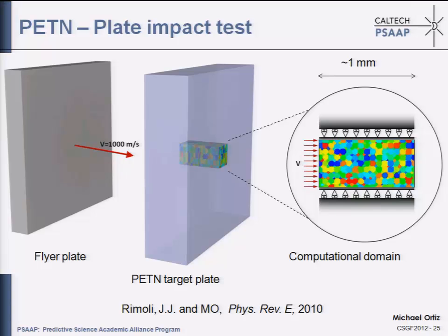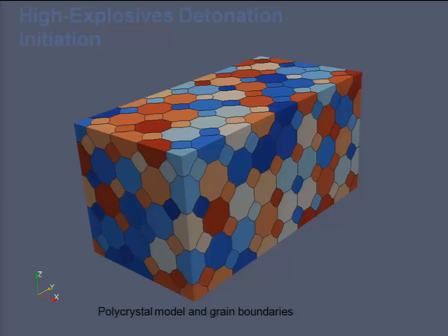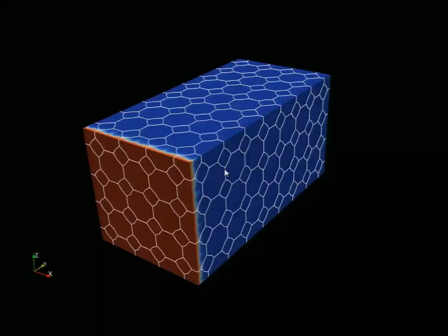So of course, the predictive challenge here is to determine when you have initiation and when you don't. And so the way we do the simulations in this case is we just take a core of material through the thickness, and we apply periodic boundary conditions around the perimeter of the core, and then this would be the computational domain. So it turns out that these days we have enough computational power that you can resolve the polycrystalline structure of the material explicitly. So here's where you can use brute force. In the old days, there were people that spent entire careers trying to characterize the effective behavior of polycrystals. So these days, at least this is a case where we don't have to be clever. We have enough computational power that we can actually resolve explicitly the polycrystalline structure, and we do. So this is a typical mesh that we would use in the calculations. So this is a typical simulation.